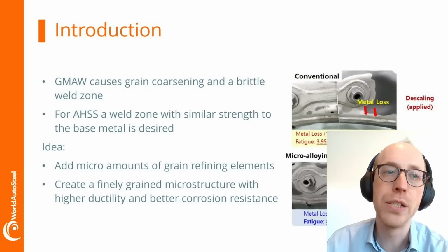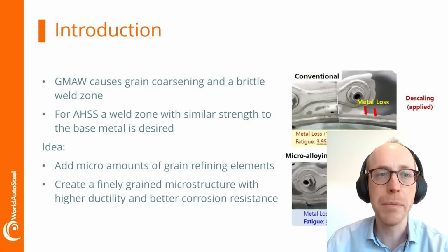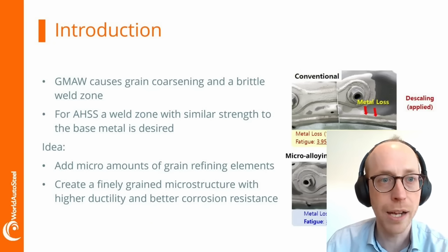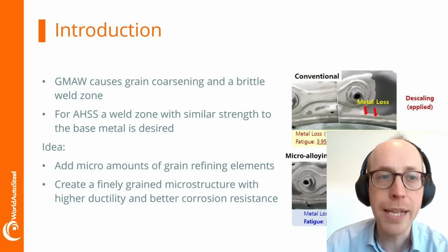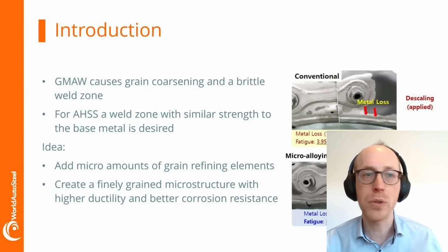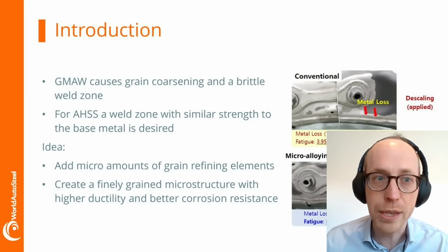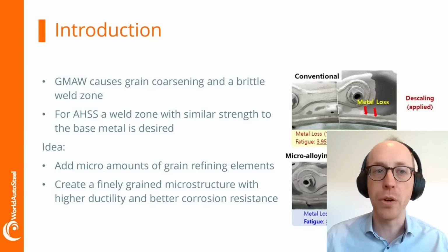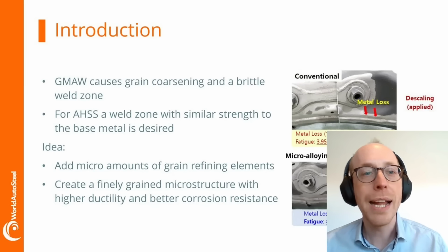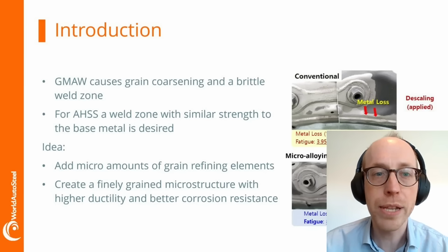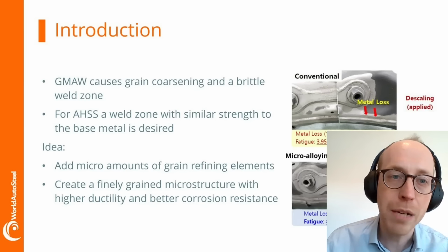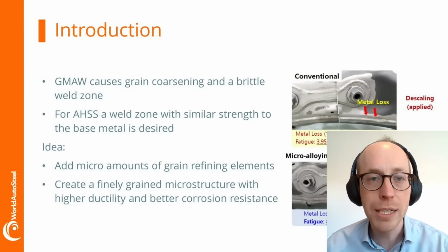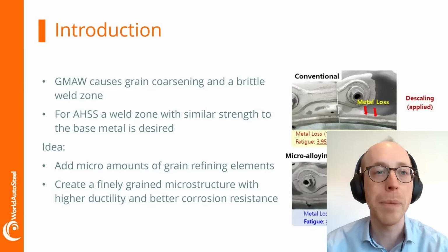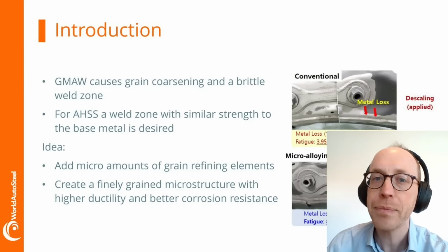So the idea is to introduce some elements through the gas metal arc welding filler wire that you don't usually have in your substrate, because either you don't want it there or it's too expensive to put it in the whole steel. And these elements are then supposed to create a finely grained microstructure with a higher ductility and overall also a better corrosion resistance.